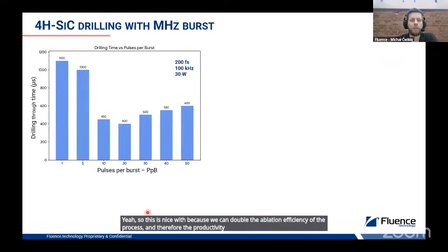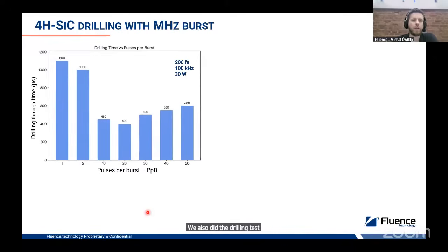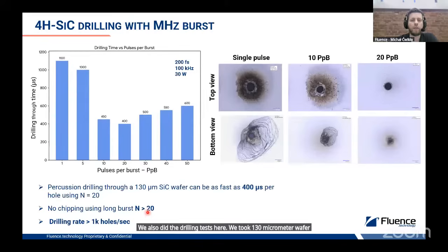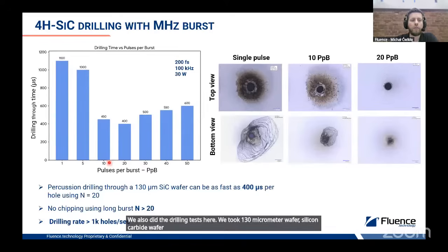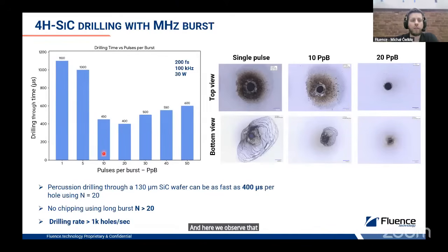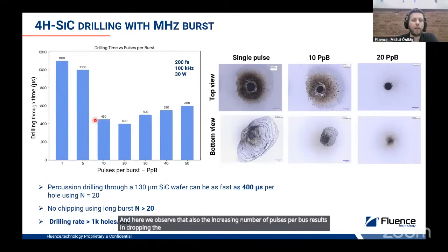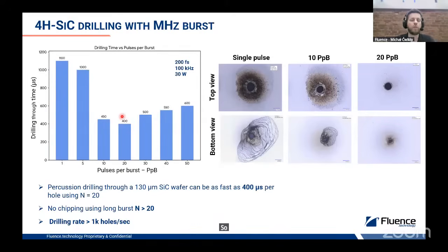We also did the drilling tests here. We took a 130 micrometer silicon carbide wafer. And here we observed that increasing the number of pulses per burst also results in dropping the drilling through time. So we managed to drop it by a factor of 3 compared to single pulse operation.